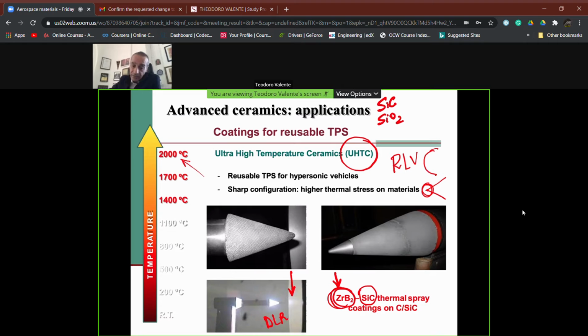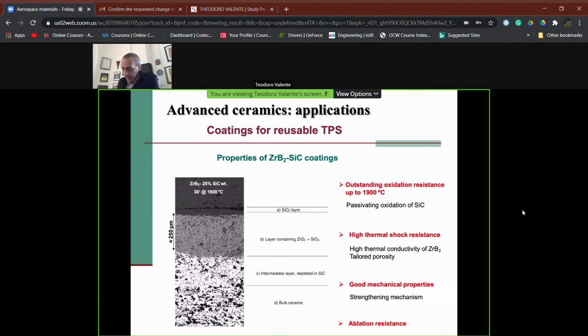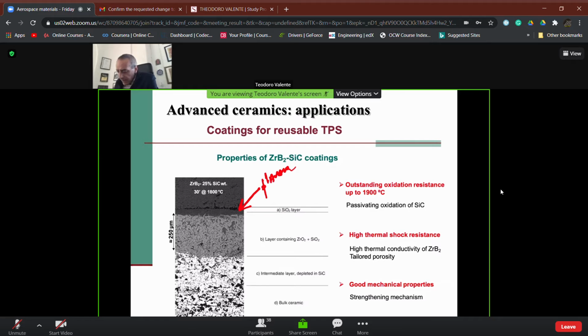And in this case, we have another very targeted niche application of composites, ceramic materials, because you see here we have two phases, the zirconium diboride and the silicon carbide, again in the form of coatings. This is an example of how this coating works. You see, this is the outer surface which has reacted with the plasma wind during testing, and so there is a degradation of the coating itself, but this is reusable.